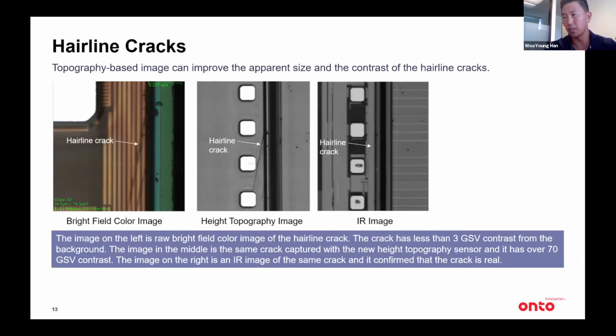So in the center, we have what we call a height topography image. To give you more details, the intensities change based on the topography of the surface of a die. With that, we get a much better contrast on such fine hairline cracks. You can see the same hairline cracks so difficult to see on traditional bright field image, even with the IR camera image. But in the center, we have a height-based topography image, and we can get a much better contrast of the same hairline crack. With this kind of high contrast image, we have a lot better chance finding these types of hairline cracks.